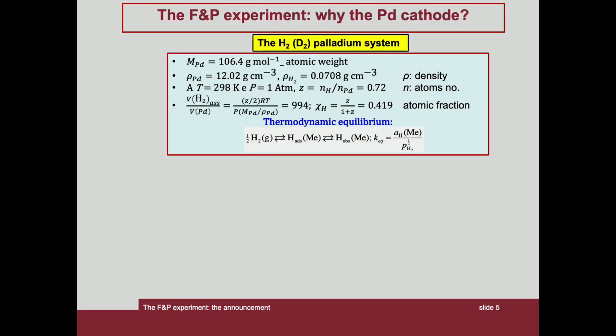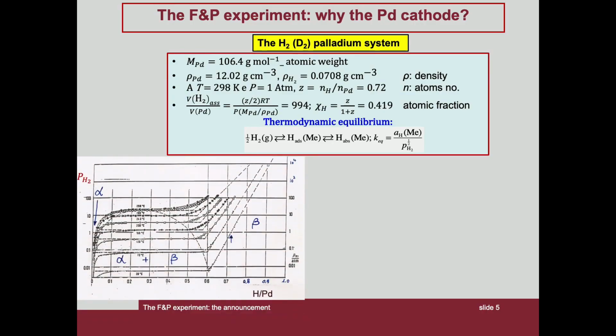The Fleischmann-Pons experiment. Why palladium cathodes? The palladium-hydrogen system is well known for forming solid solutions with hydrogen and its isotopes. It's shown that at room temperature and atmospheric pressure, 8.85 cubic centimeters of palladium, corresponding to 106.4 grams, absorb a volume of hydrogen in the atomic state which is 994 times greater. The system of hydrogen absorption isotherms as a function of the ratio of hydrogen atoms to palladium atoms shows three phase regions.